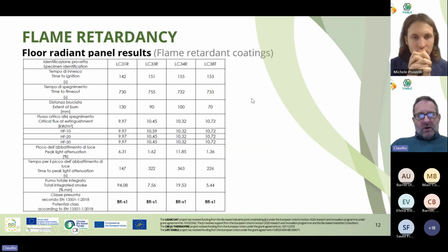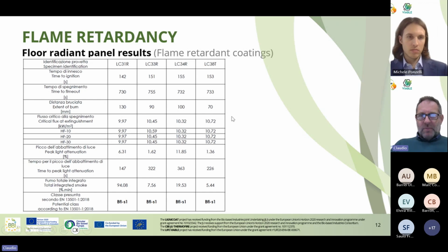As a matter of fact, we have tested our products against it, and for all of the materials that we have chosen, we have passed the BFL-S1, which is the best class you can aim at. Nobody has been speaking about the Euro classification system, but I think most of you are familiar with it. Classes are named from A to B, C, and so on. So B is not the best all in all, but it's the best you can achieve with this kind of material, because A classes are only for truly non-combustible materials. So this is an excellent result. And interestingly, one of these specimens was a sample including no added flame retardant. The fire performance was obtained only by the inherent thermal stability of lignin. And well, this is very good in my view.